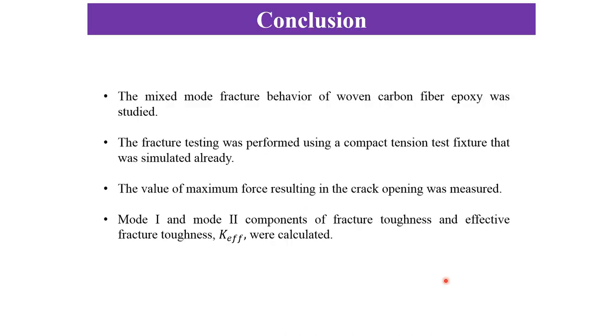So in summary, we studied the mixed mode fracture behavior of woven carbon fiber epoxy. Here the fracture testing was performed using compact tension shear specimen that was already modeled and simulated. The value of maximum force that caused the crack opening was measured, and using those values, mode 1 and mode 2 components, fracture toughness and effective fracture toughness were calculated.